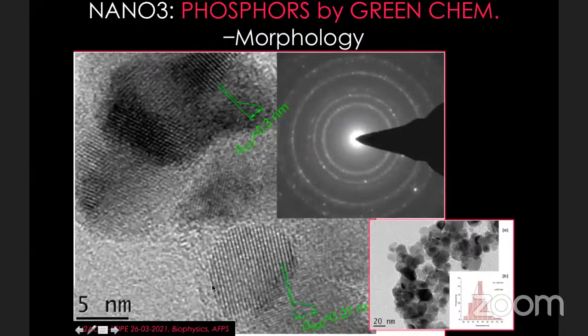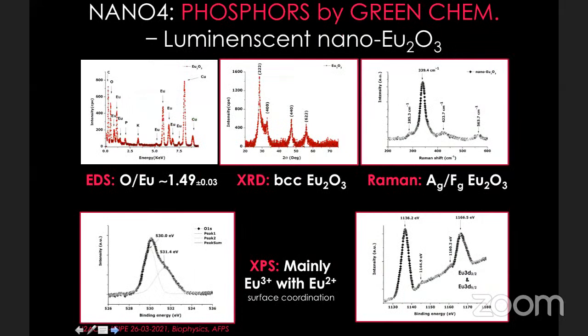Between 15 nanometers in size and 20, but they are highly crystalline. And again, when you go to run physical investigation of surface and interface, be it EDS, Raman, XRD, EXAFS, it's mainly europium 3+, and it's BCC europium oxide, and the Raman mode confirms the BCC structure and so on.